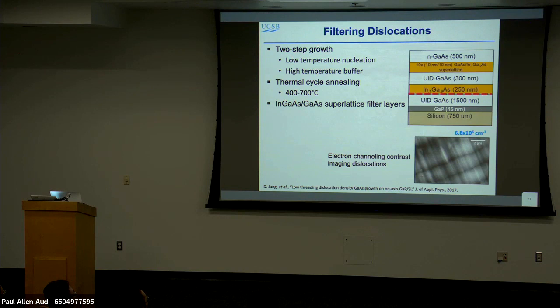We do, or three approaches, basically two-step growth, a low temperature nucleation growth, a high temperature buffer growth, and then we do thermal annealing. We take it up and down 400 to 700 degrees C in an effort to drive all those dislocations to terminate on each other. And then the third approach is to have indium gallium arsenide superlattice layers and multiple layers of those. And those, again, are known to cause dislocations to terminate. And so here's an ECCI image of it, and you can't really see very well, but you can see a couple of these dislocations. And the density is about 7×10 to the 6th. So that's 100 times lower than where we started, and you'll see the impact on reliability is huge.